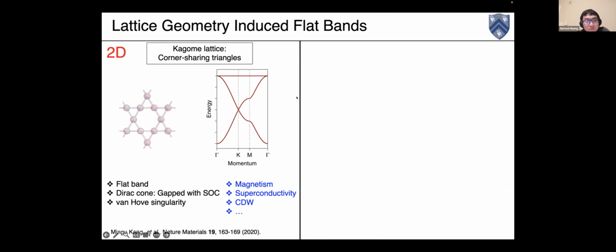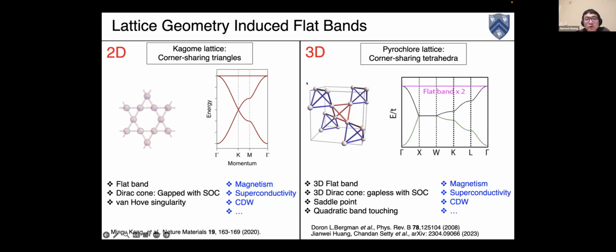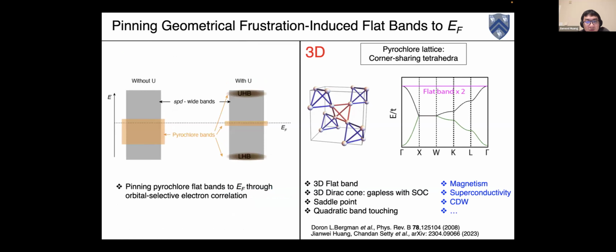Also recently we started to study the three-dimensional geometrically frustrated lattice, which is the pyrochlore lattice. This lattice has the advantage that its topological flat band is three-dimensional, but in both these cases there's an issue that we need to tune the flat band to the Fermi level to really get this strongly correlated topology into play. So one strategy we have here is that you can tune a flat band to the Fermi level with this orbital selective electron correlation effect.